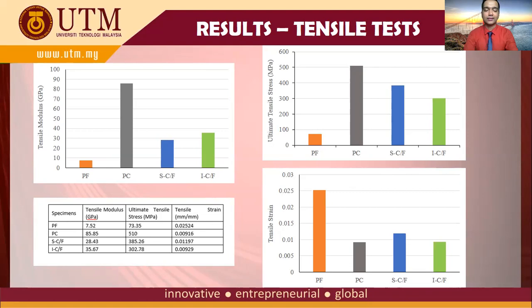On the other hand, for ultimate tensile stress, as expected, pure carbon is the highest, which is 510 megapascal, and pure flex is 73.35 megapascal. But for eco-hybrid laminates, it can improve to almost 525% compared to pure flex, that is sandwich-like equal to 385.26 megapascal, and intercalations equal to 302.78 megapascal.